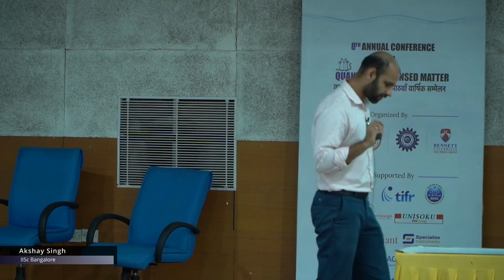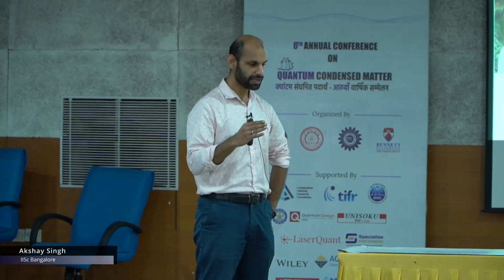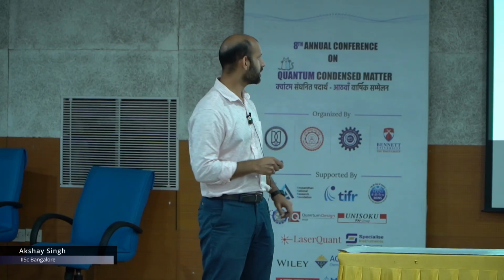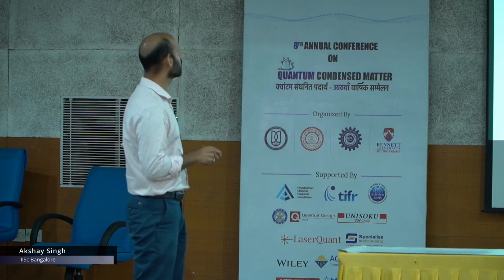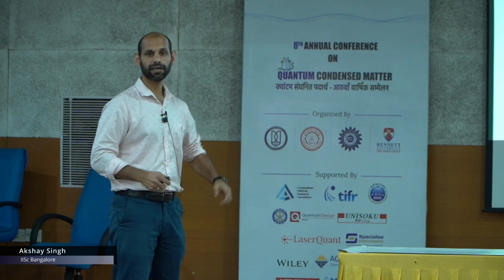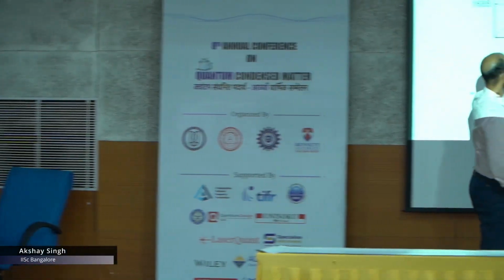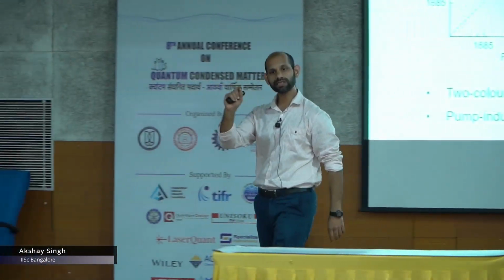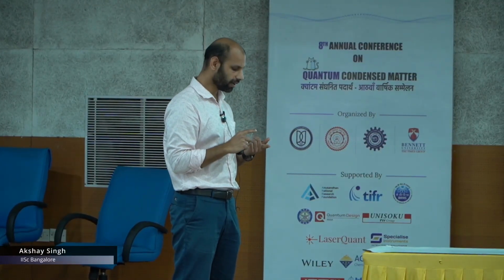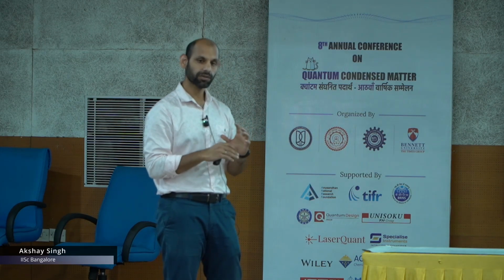In pump probe, it's a great question. In pump probe, it's not very easy to directly say if a positive is bleaching or a negative is. So you actually have to look at the full 2D pump probe signal, like the one that I showed, this whole thing in one shot, because let's say this feature starts shifting energy, it will start influencing its nearby neighbor. So you have to look at this whole feature together. You have to consider energy shifts, you have to consider energy broadenings, and that's one way that you can simulate this whole plot.